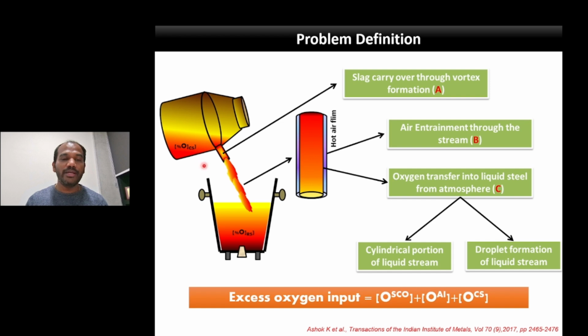The first phenomenon here is the carryover of an oxidizing slag, and the second phenomenon is basically the entrainment of air and diffusion of oxygen and nitrogen through this boundary layer. And finally, the liquid steel stream can be cylindrical, or it can break into multiple droplets, and the surface area increases, and it can encourage more. So as such, if you see this process, a lot of excess oxygen is basically going into the ladle.